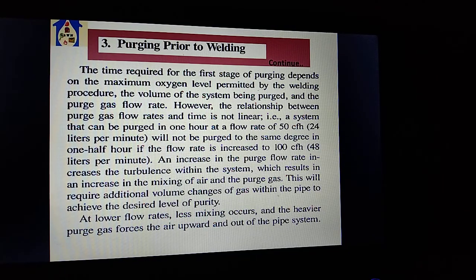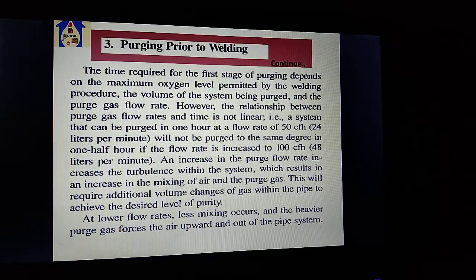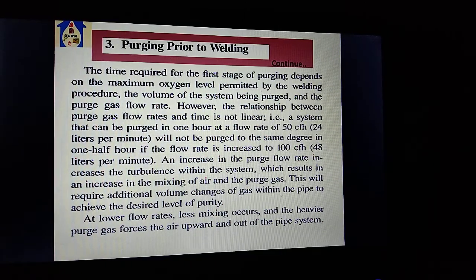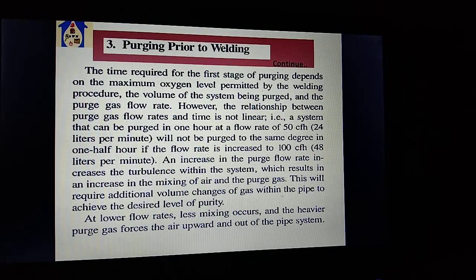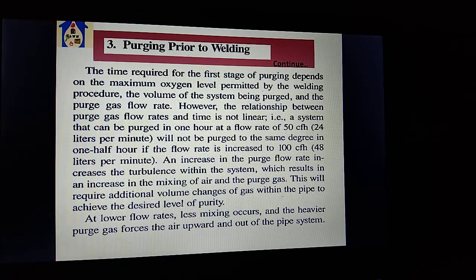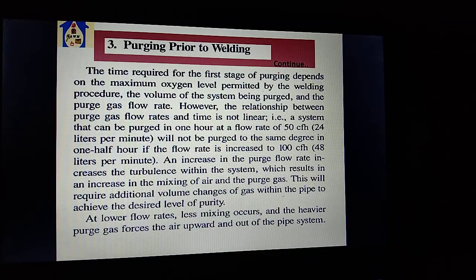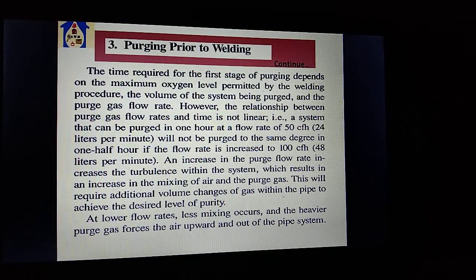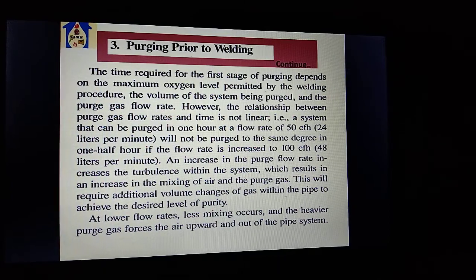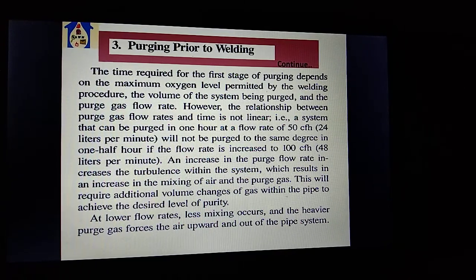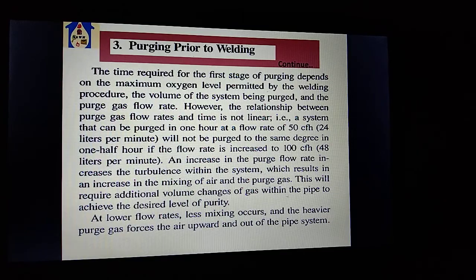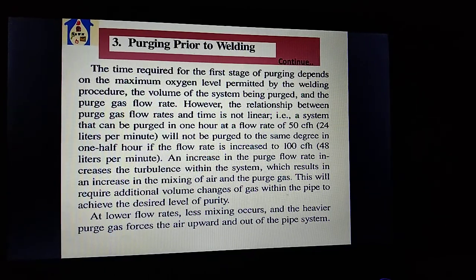Increasing the purge flow rate increases the turbulence within the system, which results in increased mixing of air and the purge gas. This will require additional volume changes of gas in the pipe to achieve the desired level of purity. At the lower flow rate, less mixing occurs and the heavier purge gas forces the air upward and out of the pipe system.